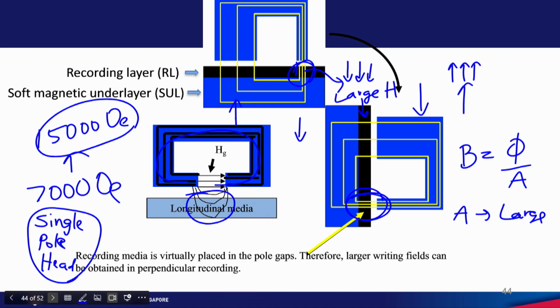Okay. So, even though you have two poles, effectively only this pole is writing information. So, it is called a single pole head, and this pole is called the return pole. The flux lines return via this pole. So, it is called the return pole, and this is the writing pole. If you compare the field strength at this pole and the other pole, the writing pole may produce 15,000 Oersted, okay, whereas this return pole may produce a field of around 1500 Oersted.